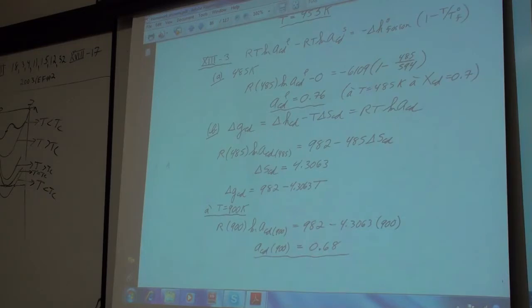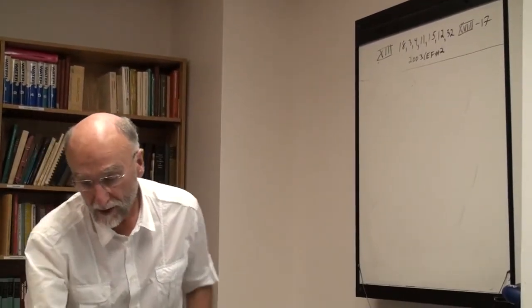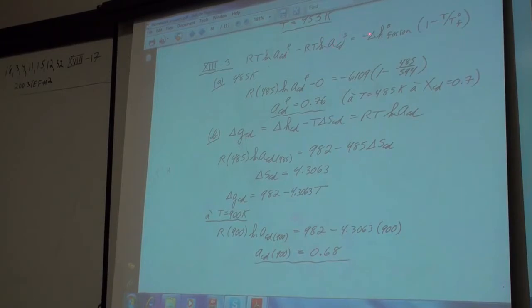So we use the equation that we use for the liquidus, along the liquidus and solidus in equilibrium. We have the equation here, RT log activity of cadmium on the liquidus minus the activity on the solidus equals the heat of fusion. The assumption, of course, is that the Cp liquid equals Cp solid. We're using a simplified equation to make it easier to do with the calculator. Okay, 485 Kelvin, that's 212 Celsius. The activity of cadmium in the solidus is 1 because it's pure solid cadmium. So this term goes to 0. So RT log activity of cadmium on the liquidus is minus the heat of fusion times 1 minus T over T fusion in Kelvin. And we get activity of cadmium is 0.76 at the liquidus temperature at 0.7.